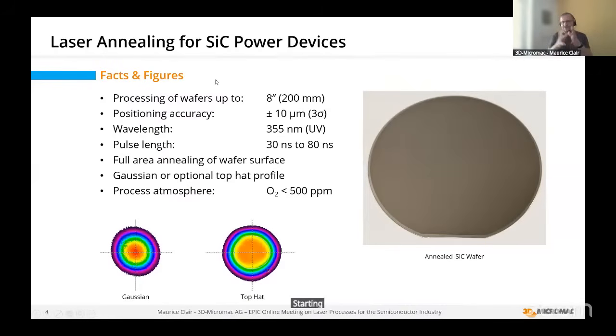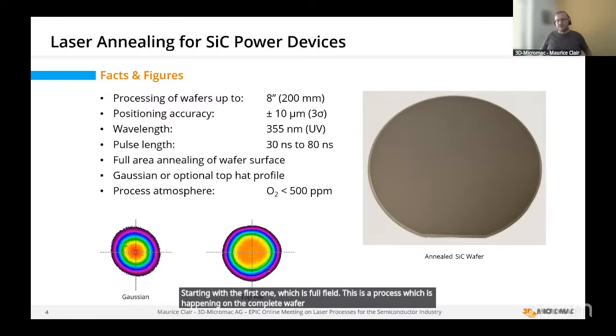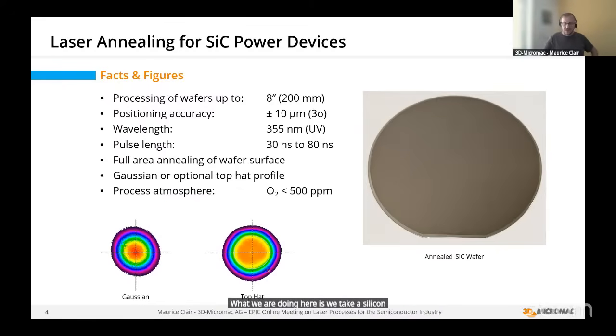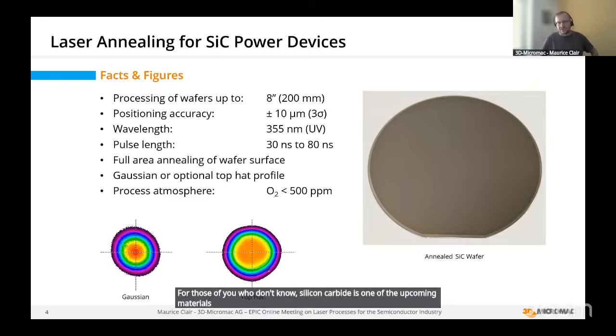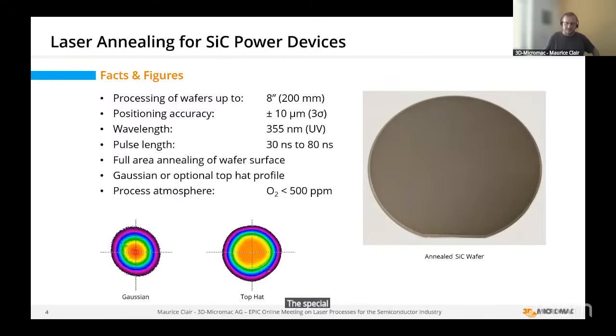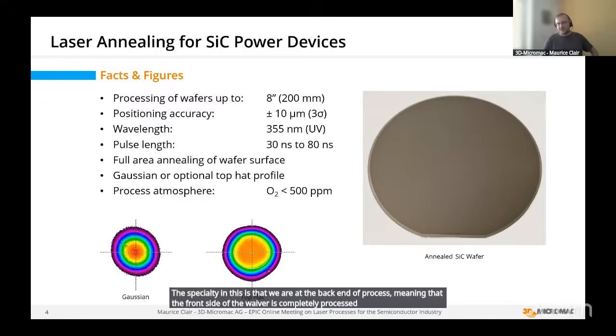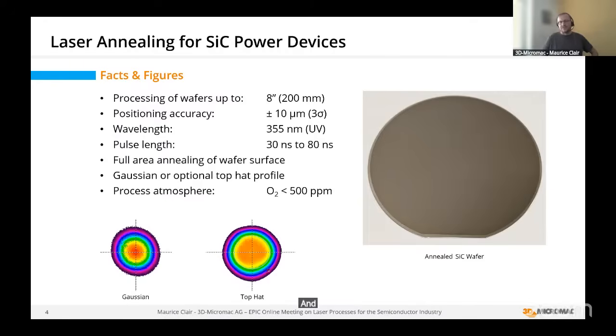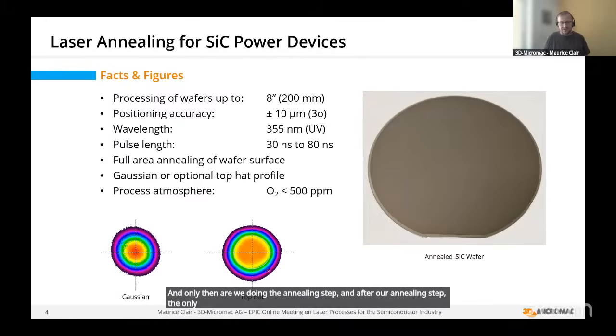Starting with the first one, which is full field. This is a process which is happening on the complete wafer. What we are doing here is we take a silicon carbide wafer. For those of you who don't know, silicon carbide is one of the upcoming materials for power electronics next to gallium nitride. The specialty in this is that we are at the back end of process, meaning that the front side of the wafer is completely processed, the wafer is thinned down, and only then are we doing the annealing step. And after our annealing step, the only steps remaining are the backside metal deposition and the dicing to the chips. So basically, we are working on an almost fully finished wafer.